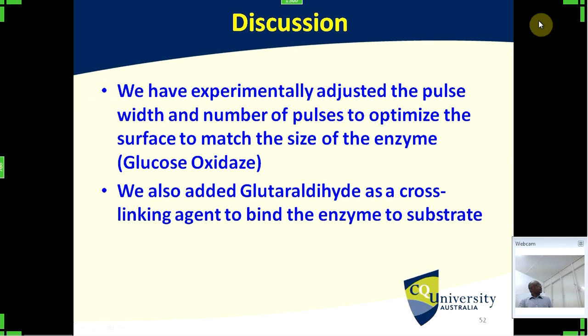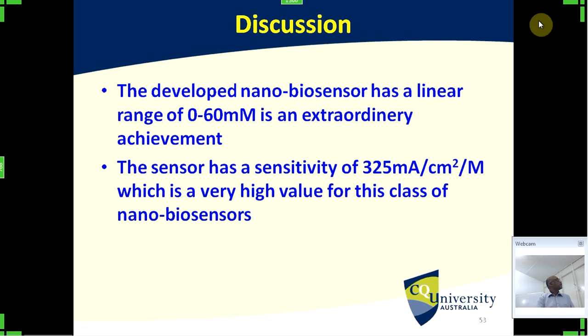So we experimentally adjusted the pulse width and the number of pulses, optimized the glucose oxidase deposition, and we got the cross-linking agent under high electric field. So this one gave us a 0 to 60 millimole linear range. It's a huge one. You don't need this much for blood glucose measurement.